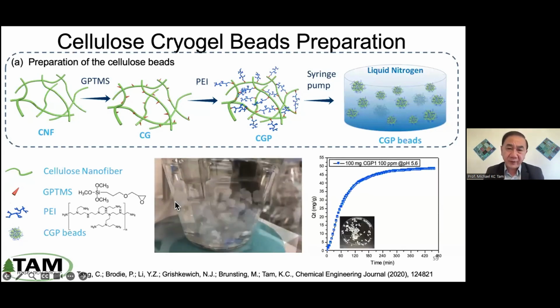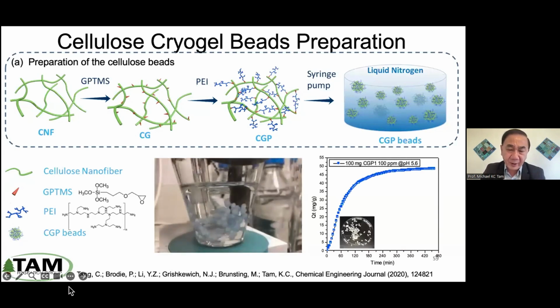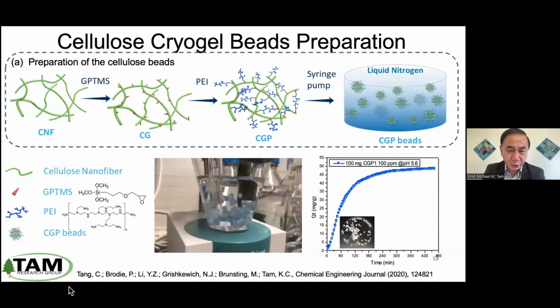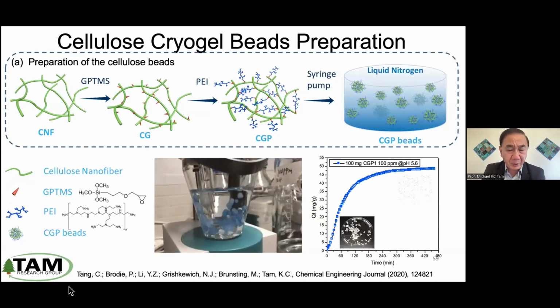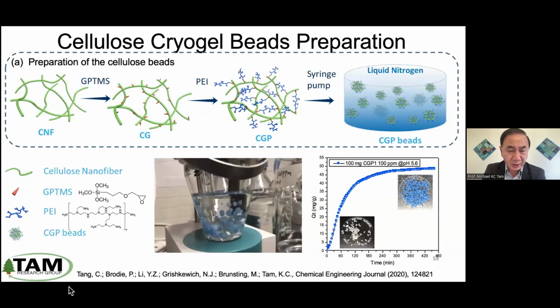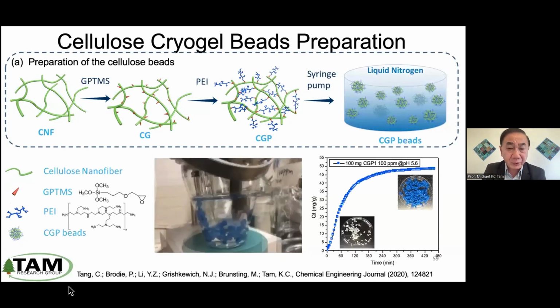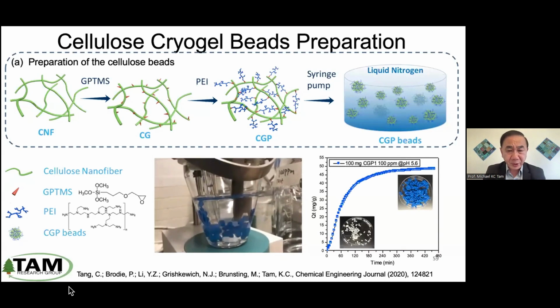So you can see here, this is a demonstration of removing copper ions from this contaminated solution, and then the bead can then be transported or used in the agriculture field for both the treatment of the soil and also provide micronutrient. So now the bead is very, very dark. It's blue now because it's saturated with copper ion, and we can measure the kinetics at the same time.